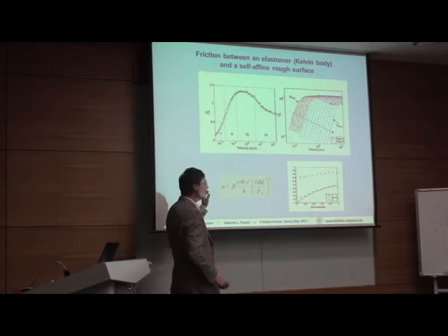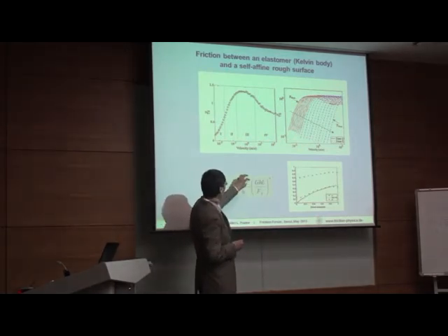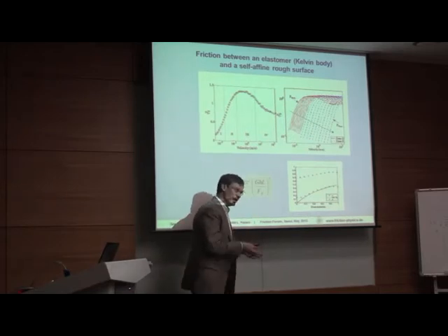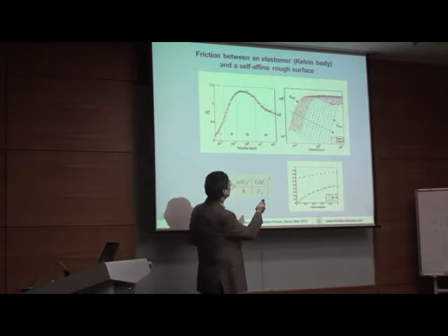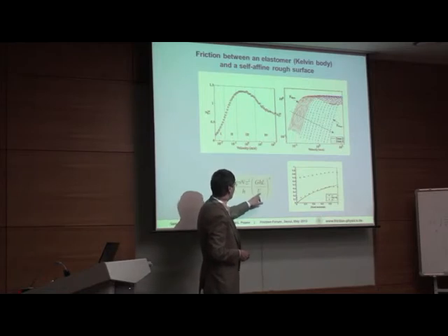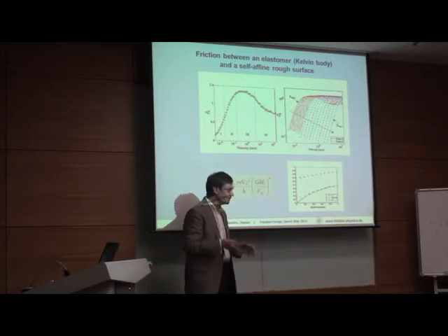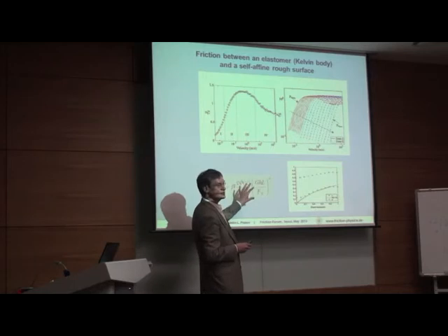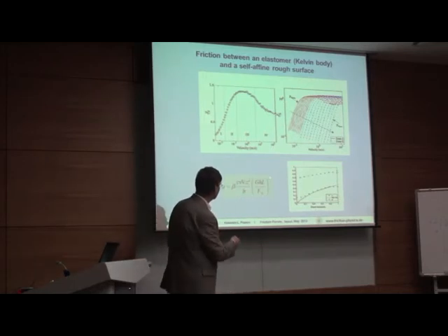There are some empirical results, for example, we see that mu is always proportional to the square of the gradient, and it only depends on F divided by the shear modulus. If we change both, we always get the same result, if other things are equal. And then the only thing we have to get is this power alpha.